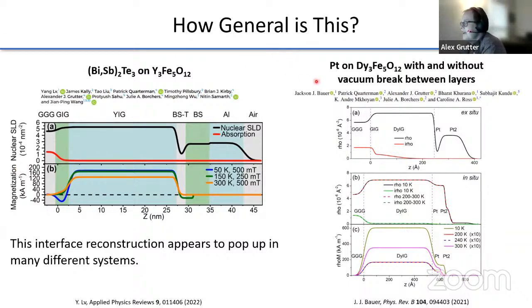So the idea being that if you grow your dysprosium iron garnet, for example, and then you grow platinum on top, if you do this in separate chambers and then transfer the dysprosium iron garnet through air and then grow platinum, you get a really low density, low quality region right at the interface.